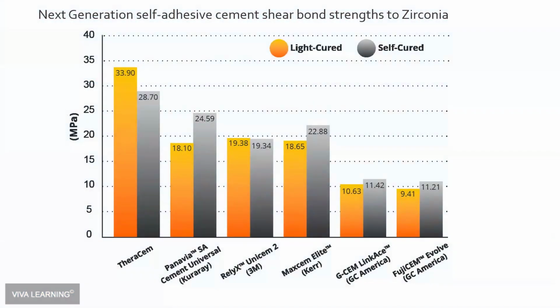And we can see that exhibited in this chart here that shows the next generation self-adhesive cement shear bond strengths to zirconia in light cure mode and self-cured mode. You'll see that even though all of these products contain MDP, they don't all have the same bond strength to zirconia. That's through a combination of enhanced bonds due to, again, messing with the ratios and optimizing them, as well as perhaps an inhibitory effect in certain situations.